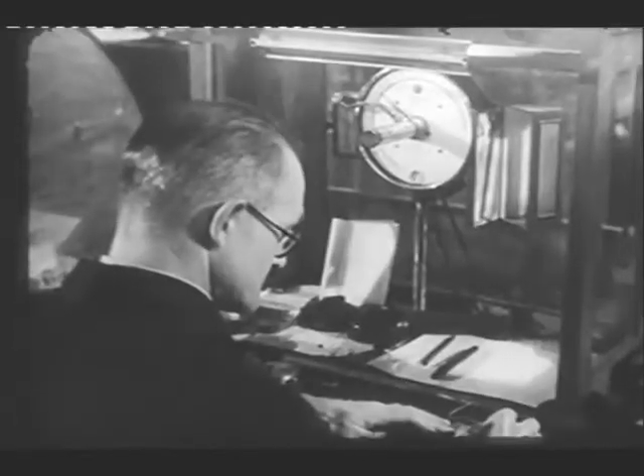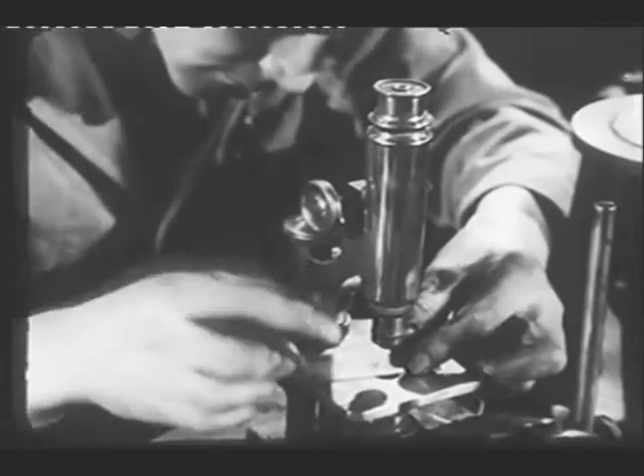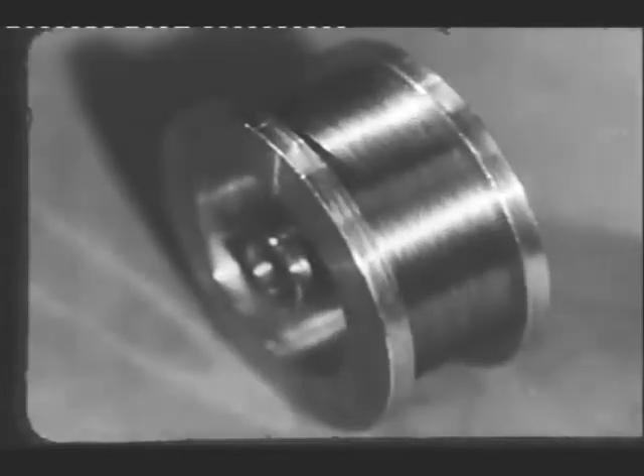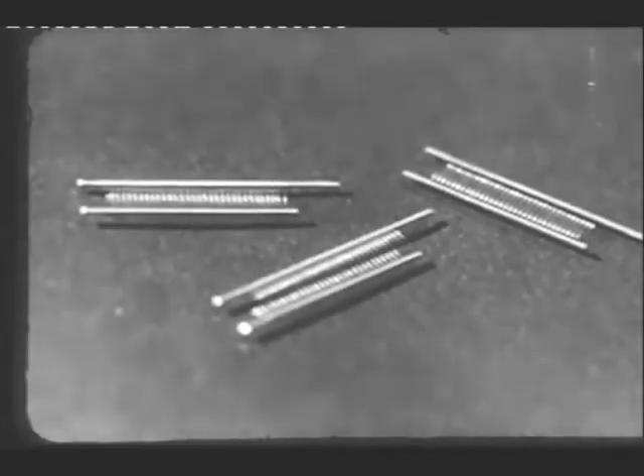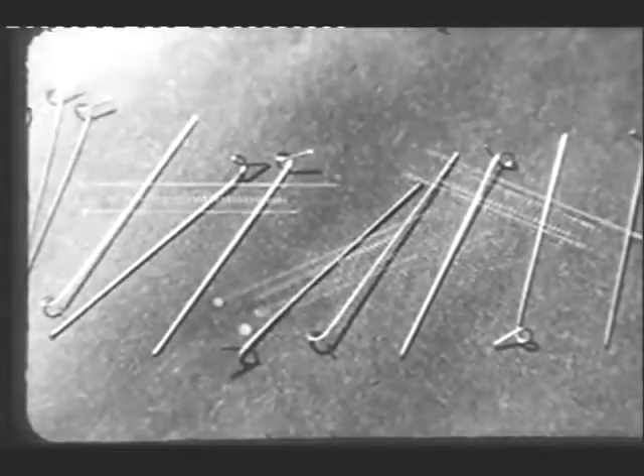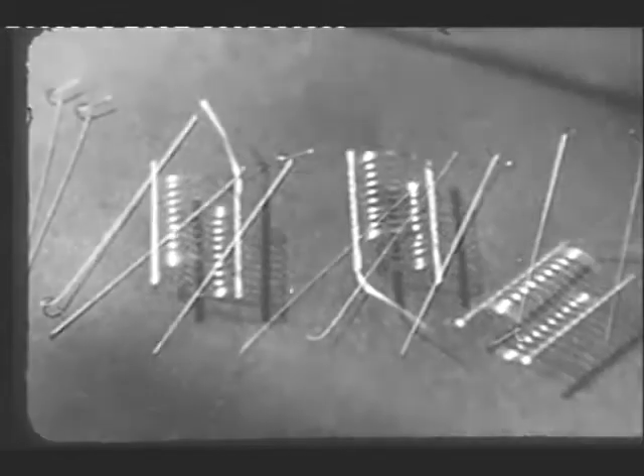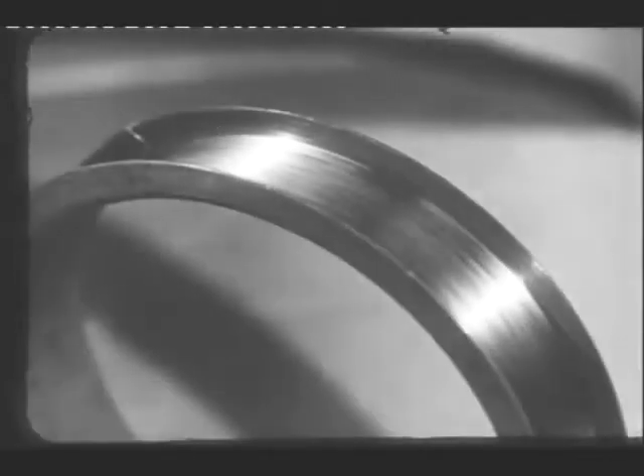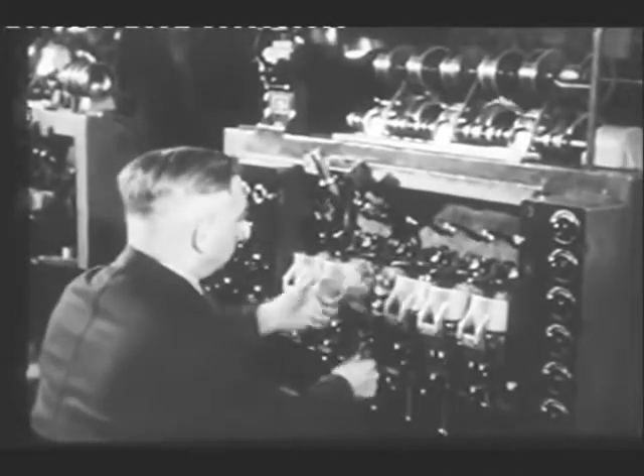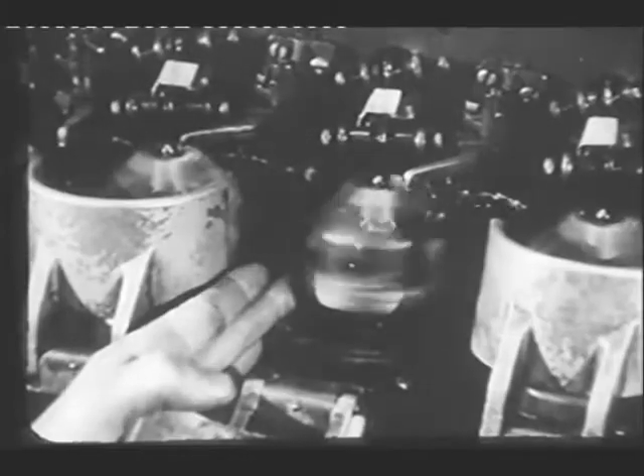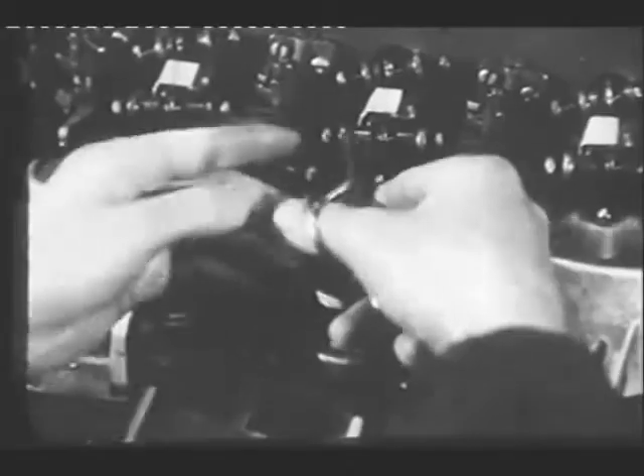Such very fine wire cannot be measured by normal instruments. Its diameter is therefore checked by weighing a known length of wire. It is also examined for roundness under a microscope. Molybdenum wire is also required in valve manufacture. For example, it is used for valve grids and filament mandrels. The molybdenum wire is produced from its ore in a very similar way to tungsten. Coiled tungsten wire for valve heaters is produced by winding the tungsten wire on a mandrel of molybdenum wire and later dissolving the molybdenum with acid.